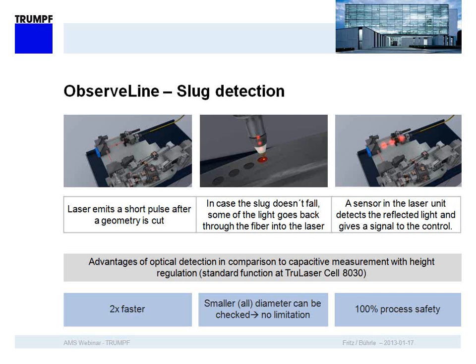Another very unique feature that we have built into the machine is observe line. This is what we use to deliver better quality or to make quality control of this machine. And how this function works, if you have paid attention to the video, it was just a very short sequence. But what is done is the laser emits a very short pulse after we have cut a geometry hole. This laser pulse of course goes through the cutting optic to the position where a hole is supposed to be. Typically, the slug has fallen out of this hole, and nothing will happen.